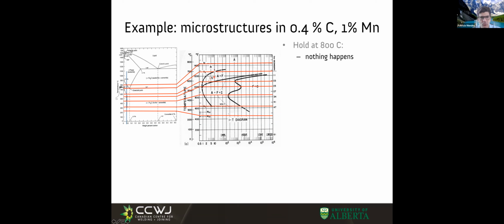So look at this diagram - this is different than the one before. First it precipitates primary ferrite and then keeps going. Let's go to this other line at 600 degrees. If we do our hold at 600 degrees, what are we going to see? Some amount of primary ferrite, and then of course we'll start transforming into pearlite. So at this temperature, in which I should have ferrite and pearlite, what it says is I would have a relatively little amount of primary ferrite, and then the rest is pearlite. The amount of primary ferrite we're gonna see in this steel quenched in these conditions is smaller than what we see thermodynamically, because now we have some kinetic issues at play.